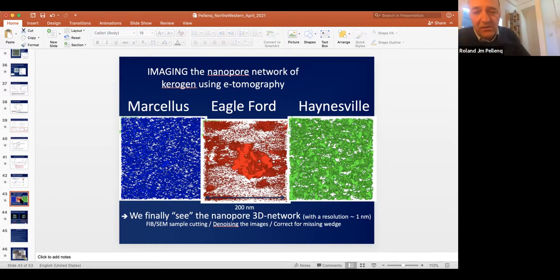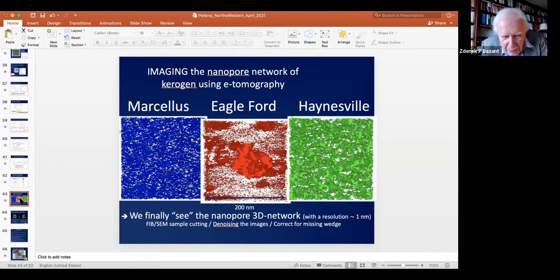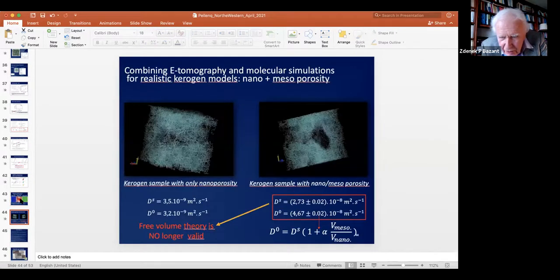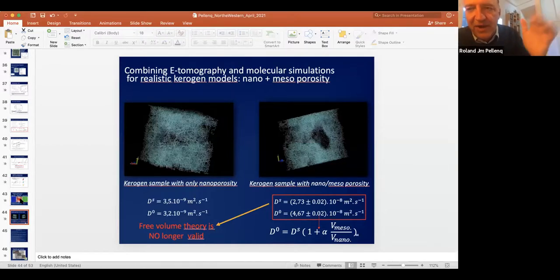So those experiments were at the scale of 200 nanometers. Your samples are taken horizontally from the shale, so there is no direction in there within the bulk, but yes, we can actually put them under anisotropic conditions. We can do an NPT simulation of those. We fix a pressure, but this pressure doesn't have to be the same in all directions. So we can have a P_zz pressure which is larger than the rest, for instance, and that will simulate this bedding plane or whatever it's called. The idea that you have a pressure in one direction. Obviously, I don't know the way to orient the big pores in the first place, because the mechanical response will be linked to the way those are oriented.